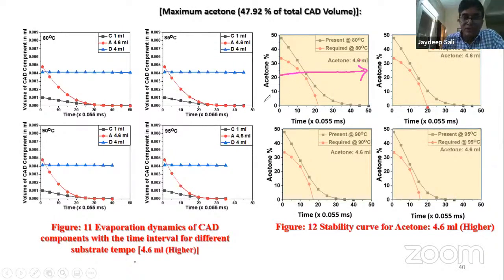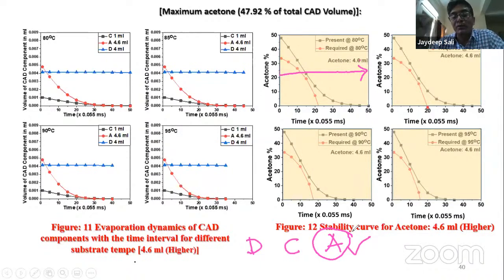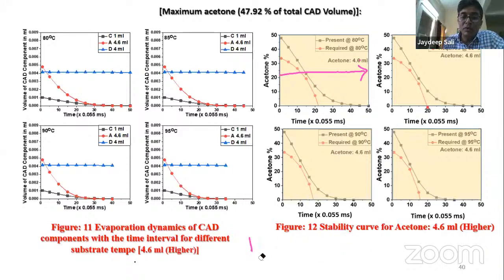So the important point is that when you form a precursor solution for the deposition of perovskite thin film, we can have a specific volume of the first solvent DMSO, a specific volume of the second solvent cyclohexane, and the third solvent acetone. Depending on the proportion of acetone, we can have different phases of microemulsion, whether it will be stable or unstable. If it is unstable, for how much time it will be unstable and for how much time it will be stable during the thin film formation, that we can control. Due to this, the microstructure of the thin film also changes, and the change in microstructure has an effect on the optical and electronic properties.